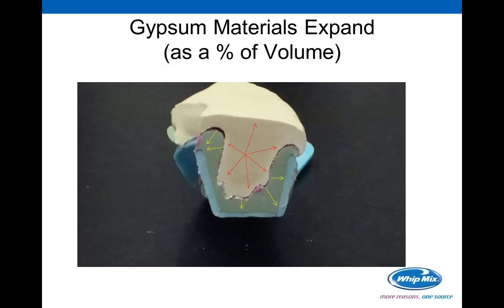Now, if we know that, as I told you before, the reported expansion is at 2 hours, most of you have poured that die stone, you've waited 1 hour, maybe, and then you've pulled that stone out of that impression, and that stone will continue to expand. It'll expand to the 2-hour point, which may be at 0.08, or it may be at 0.28 expansion. You've got a die that's quite a bit larger than that original reproduction of the prep in the patient's mouth. So you should have a crown that, for lack of a better term, fits like socks on a rooster, as they say.